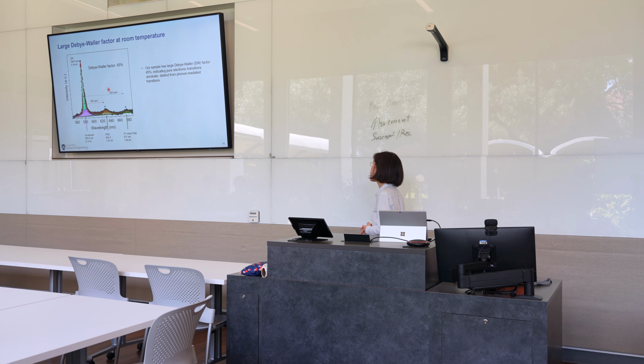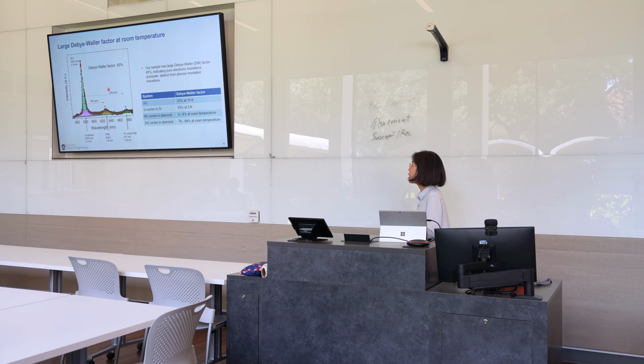Now this 45% Debye-Waller factor for our sample is still very decent, even if we compare to some other very famous single photon emitters. For example, the divacancy in silicon carbide, the G center in silicon, and the NV center in diamond. You can see these values are not very high, and some of them are even at low temperature. Of course, there are also other single photon emitters with high Debye-Waller factor, for example, the silicon vacancy center in diamond. So there's still room to improve for single photon emitters in boron nitride.